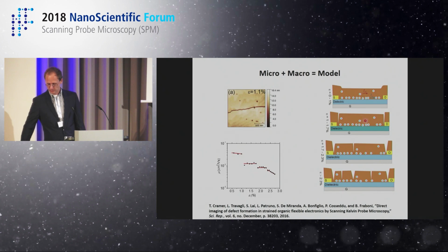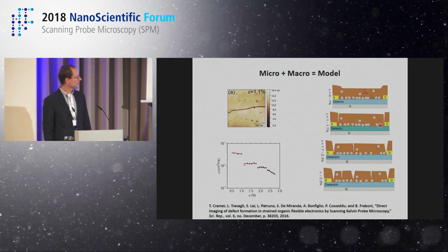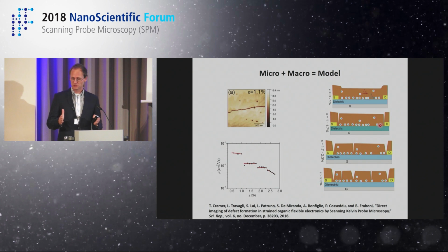What is important here is that at the surface, these cracks might be large. But of course, at the interface is where my charge transport happens. Here it's very relevant to think also about adhesion. So the adhesion of the microcrystal to the surface is something that we assume helps to stick these gaps together, so that even though I see at the surface it cracks, I still know that there is some possibility for carriers to overcome them.